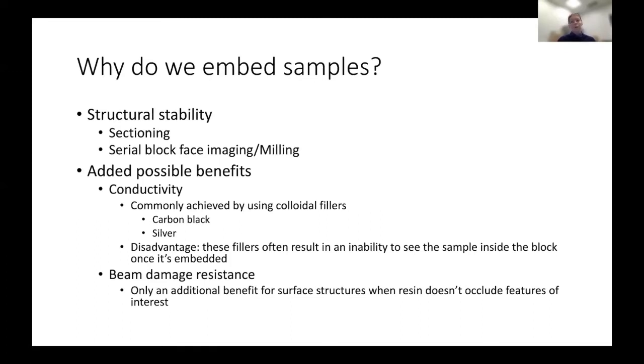damage better. So even if you have a sample like a tooth, you might still consider embedding it rather than just polishing it, because the resin, once it infiltrates your sample, can help it stand up to beam damage better, help keep it more stable while you're imaging it. A word about embedding only for beam damage resistance, though. If you're looking at a structure and you want to measure the diameter of a hair, for example, don't resin embed it. It's not going to help you. Just image it in the SEM, because if you coat it in a resin, obviously it's going to change the diameter that you can measure. So keep in mind, it's not useful for everything. Its usefulness is only as useful as your experimental goals and how well your method aligns with them.